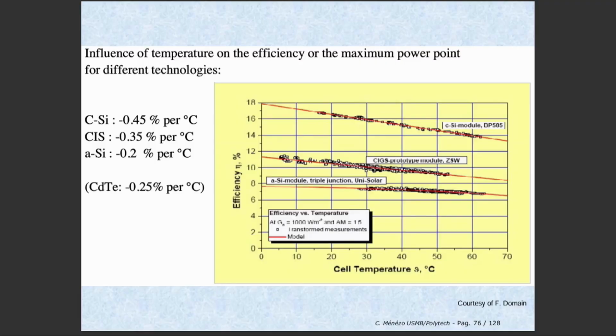Okay, so I told you the main advantage of crystalline silicon is that it is quite stable, quite mature. We have a lot of experience and feedback on this technology and so on. The main inconvenience is that it is the most dependent on temperature. It's around 0.5, 0.45 percent per degree. Whereas, as I told you, amorphous silicon, for example, is less dependent. It's 0.2, but the efficiency is lower also. So you can have different evolution of different technologies depending on temperature.